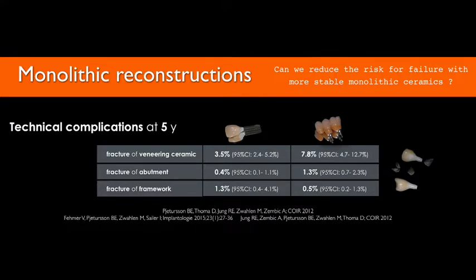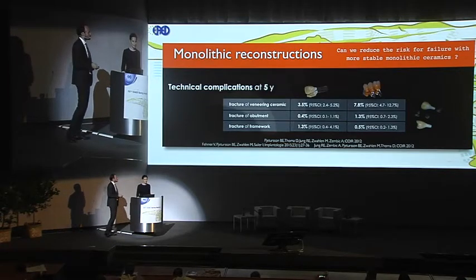The truth is not 1 year, 2 years, or 3 years. So here we are showing you fracture of abutments is no longer an issue. Fracture of the frameworks is no longer an issue. But the biggest issue that we are facing is fracture of the veneering ceramic. 3.5% for the singles, close to 8% for the multiple reconstruction.